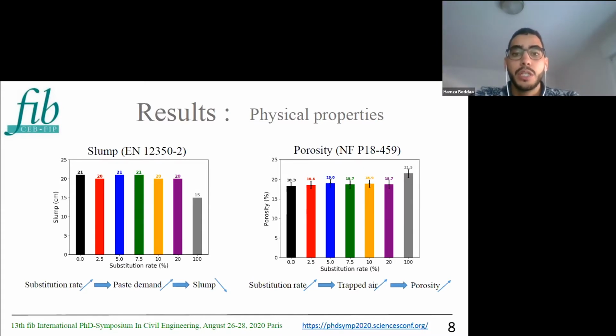The slump of the fresh concrete was measured using the Abrams cone, and the results show that up to 20% of substitution, the slump of the concrete based on shells is similar to that of the control one. However, a significant decrease of the slump was measured for a total substitution of coarse aggregate by the shells. So the decrease could be attributed to the important paste demand of shells due to their high specific surface area.